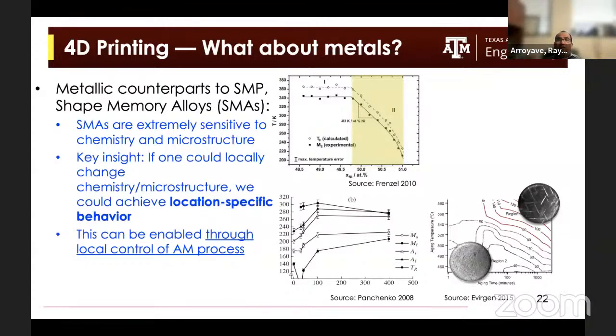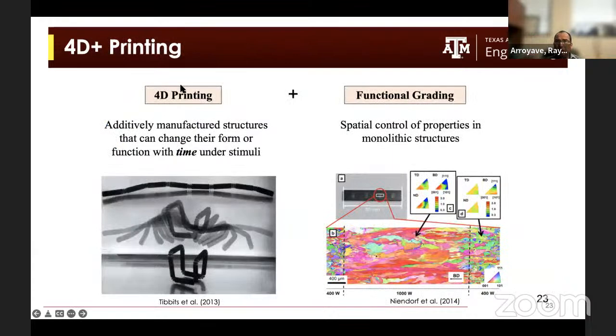Okay, so the idea here is, if we know that these materials are highly sensitive to chemistry and microstructure, can we tailor the chemistry and microstructure of a material that has a uniform feedstock composition by just locally controlling the process conditions? So we're actually proposing here 4D plus printing, where we have the traditional 4D printing characteristics of being able to fabricate things that respond in time. But the idea here is that we actually want to locally change the composition, so we control this actuation in time and also in space, right? So the idea here is, can we actually print different locations of the part with different processing conditions? So every region of the part has different chemistry, and therefore we'll have different transformation behavior when we apply a particular type of stimulus, okay?